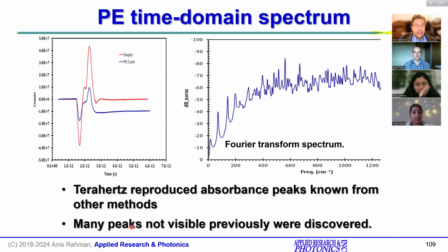So another calibration: this is the polyethylene spectrum, which is a common window material used for FTIR and that kind of spectroscopy. Polyethylene has a known spectrum, and therefore when we do the characterization, we eliminate the polyethylene peak, and all other peaks then become important, and we go on explaining them.